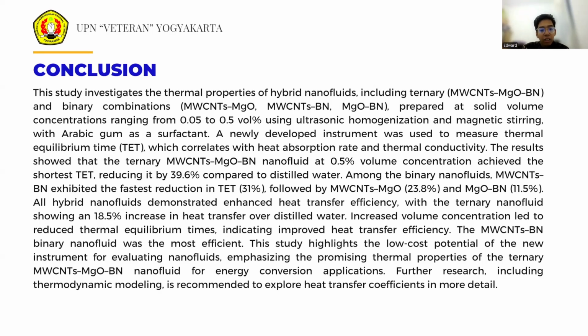This study also clearly established a correlation between volume concentration and thermal performance. As the nanoparticle concentration in the base fluid increased, the thermal equilibrium time decreased, meaning the fluid reaches thermal equilibrium more quickly. This implies that higher concentration nanofluids have better heat transfer performance. Specifically, a 0.5% volume concentration was identified as the most effective for achieving optimal thermal performance. The study concludes that increasing nanoparticle concentration leads to a corresponding enhancement in the nanoenergy heat transfer by the nanofluid, which is essential for improving the efficiency of heat transfer systems.